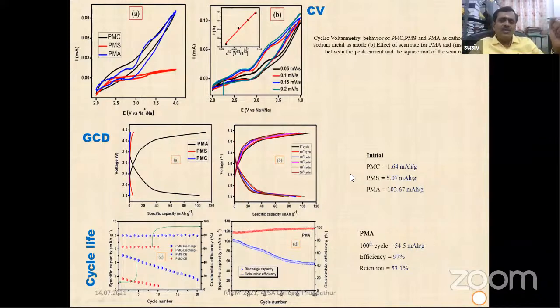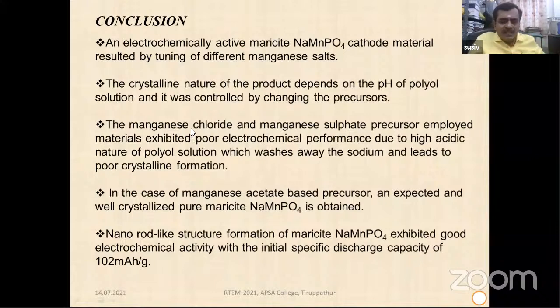That gives the conclusion that the materials employing manganese chloride and manganese sulfate precursors exhibit a very poor electrochemical performance due to the high acidic nature of the polyol solutions. That will wash the solution and it causes the poor crystalline formation. Therefore, while using the manganese acetate precursor, we expected the well crystallized pure maricite NaMnPO4, which gives good electrochemical properties such as 102 milliampere hour per gram, and it also sustains very well.